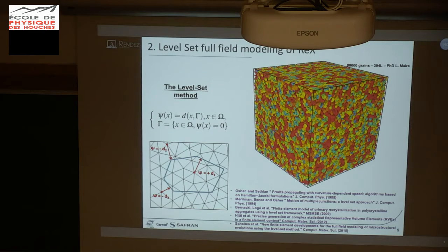In the picture on the left side at the bottom, you can see a grain interface in blue. And you can see that a priori in level set description, the grain interface is not conforming to the finite element mesh in black. But what we use in each integration point of the finite element mesh, for example the black points, is a mathematical function, described by psi here, which is the Euclidean distance of each node to the blue interface. And what we use finally is a distance function to describe the grain interface in the finite element mesh.